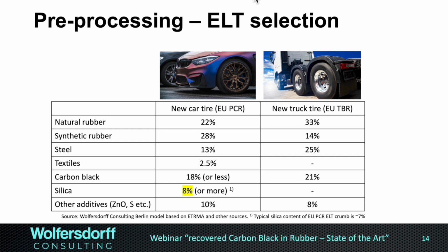Silica in the tread has replaced carbon black because of its higher performance in two of the key performance criteria. So we have 8% or more silica in a new car tire. My analysis on the crumb of used tires already shows 7%, so we can expect in a new tire much more than 7% and much more than 8%. Of course, we've got other additives. We've got the activator zinc oxide, which should have reacted to zinc sulfide. We might have some free sulfur as well.